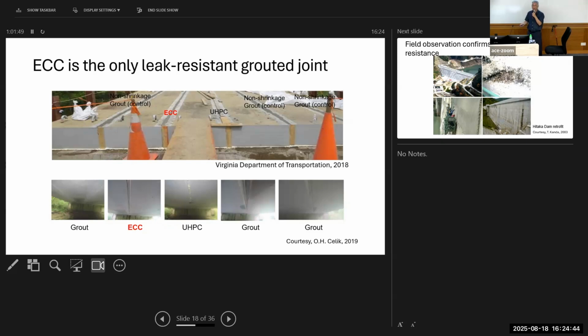And this is not surprising to you now, because the material, even though it can experience very high shear loading at the joint, where the adjacent beams can move relative to one another, the crack, even if it damaged the material, the crack width becomes very tight. And not only tight crack width, but they repair themselves. Okay, that is not the case with UHPC or with their conventional high performance grout. The UHPC with very high compressive strength actually does not help. This is not a case of compressive strength, right? It fails because it lacks durability due to water leakage. And that's what they want to stop.